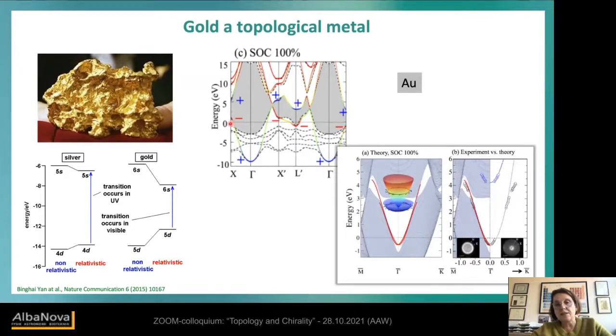And here is the electronic structure of gold, and it's a metal, but you see it's the same effect as what I show in my drawings, that you have here this d-type band. Here is the Fermi energy, and here we have the s band, which are crossing, and here you nearly have gap situations, so the gold can also be ionized, and you can put additional electrons in compounds, so you get maybe an insulator. And indeed, here also we could show by 2-photon electron spectroscopy that the conduction band is connected to the valence band with this special surface state.